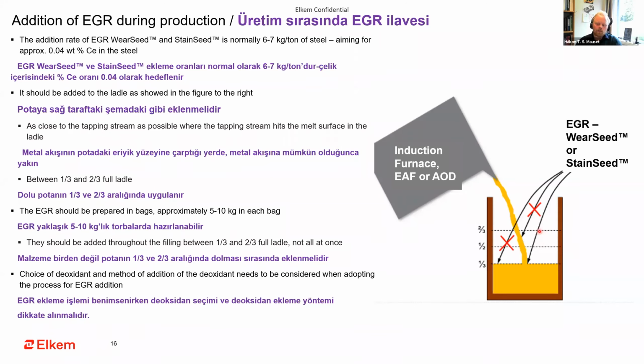And it's also very important where you actually hit with the EGR. You should not hit directly into the tapping stream, because then it can just bounce off. You should not hit close to the ladle wall, because then the material can just stick to the ladle wall. The bullseye is here, as close as possible to where the tapping stream is hitting the metal in the ladle, because then the alloy will be dragged down into the steel, and it will dissolve before it manages to float up again.